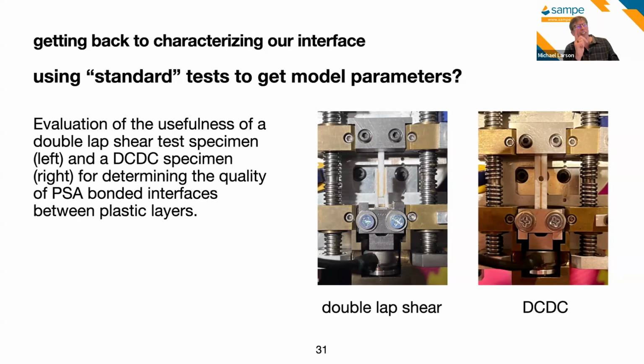And since in general, these things are primarily driven by shear in a temperature application, again, it's bulk materials in their linear regime, not the 90 degree peel by any chance, this would seem to be intuitive. But pulling these things apart, we found specimens to be unstable, with different initiation sites.